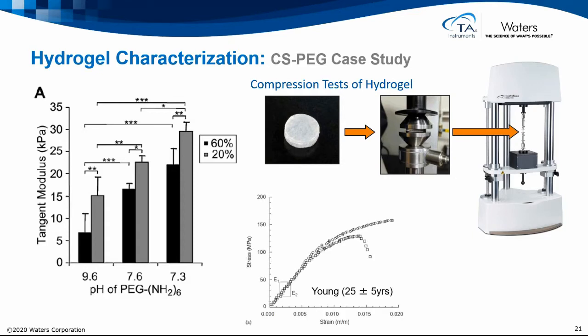So I'm actually going to pull back the example from the dental application, where the stress versus strain produced this modulus, a line that looks something like this, although that should be straight. A straight line fit here, but in many of these materials, it's nonlinear. In the dental application, it's nonlinear because of yield. But if we were going to measure the tangent modulus at, in this case, 1% strain, then it would be the tangent of the stress versus strain plot here and here. So those would be the two tangent moduli for these two samples. Sometimes you'll see that and wonder, what's the difference between Young's modulus and tangent modulus? Young's modulus will be this classic linear fit in relatively linear samples, and tangent modulus will often be used for nonlinear samples.